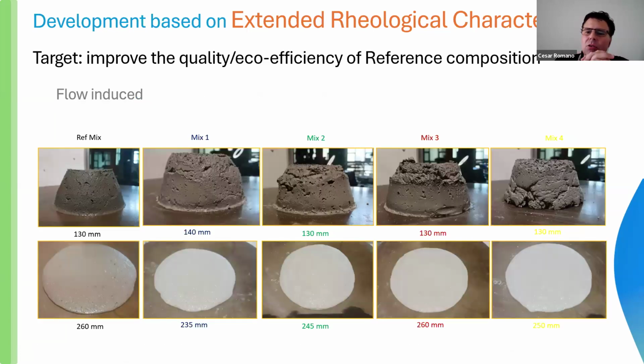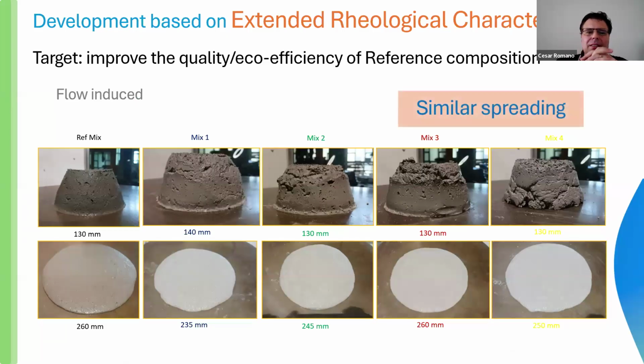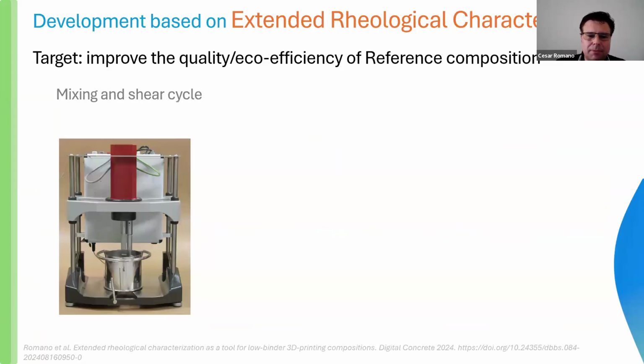But when we apply the concept of flow table test, they presented similar spreading during the flow induced here. Because of this, we can't use it for important information about the quality of the composition. It's not possible to use just a flow table test. It's just an indication, a visual indication of the spreading of the material. And we didn't have any good information about that.